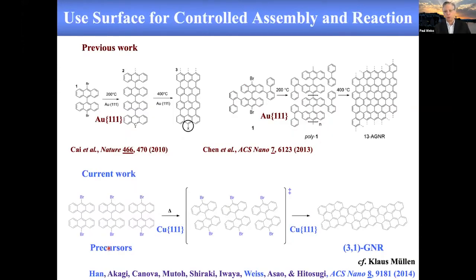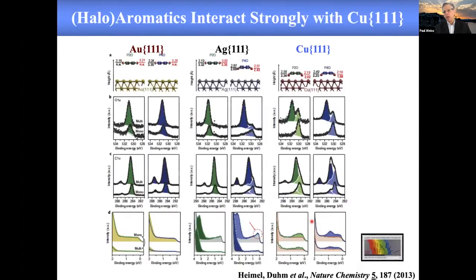And then what Patrick was able to do, because we had developed this Ullmann coupling chemistry over the last 25 years in our group, was to design a precursor, much like Klaus Müllen does at the Max Planck Institute, and know what the intermediates on the copper surface would be and how they would interact, such that when he raised the temperature and reacted them, we'd get these precise graphene nanoribbons. And that works. And the reason we use copper in this case is it's much more strongly interacting with the aromatics on the surface than are the silver and gold in its column of the periodic table.